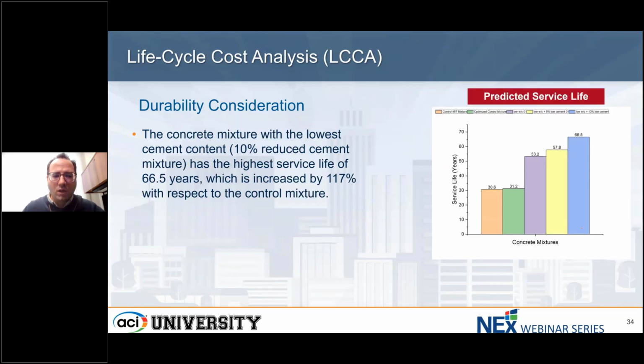These are the results for deterioration. So you see the predicted service life for the different concrete mixes. For the control one it is around 30 years, and it increases to around 53 years for the low water-to-cement ratio system, and to 66 years for our optimized sustainable low cement system. So that's almost a 117% increase in service life when comparing that system with the control system.